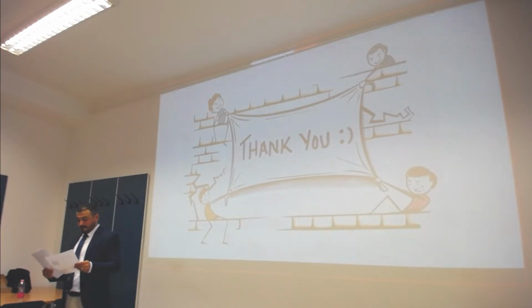And in connection with thesis 6, I think it is acceptable according to the results explained in the dissertation. And in my opinion, I would suggest adding to the thesis that among the pass speed, ironing spacing, and flow rate, the ironing spacing parameter has the most significant effect on the average roughness. As you mentioned, I found that ironing spacing significantly impacts the roughness values. I think it can be a more complex statement according to these measures.